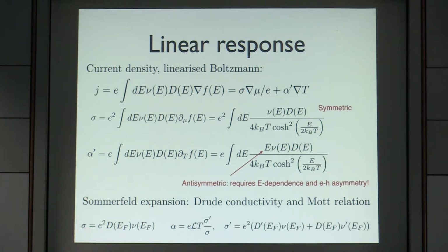What you notice is that this part is even in energy. This is odd in energy. So this means that in order to have a finite alpha, you have to have an odd component in this. And this is not that easy in metals, because in metals typically the density of states and the diffusion constant are almost constant. Which means that typical alpha in metals is actually 0.